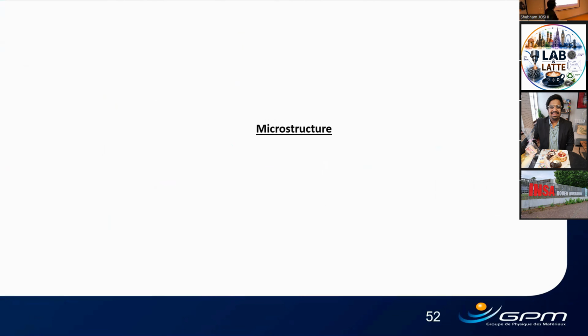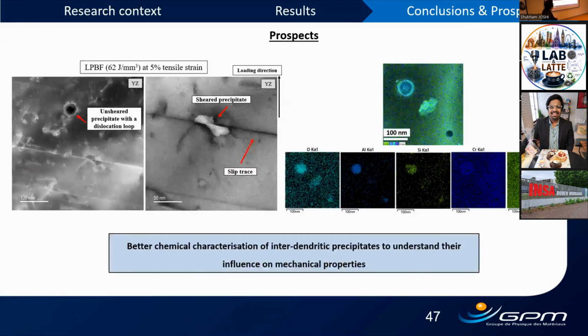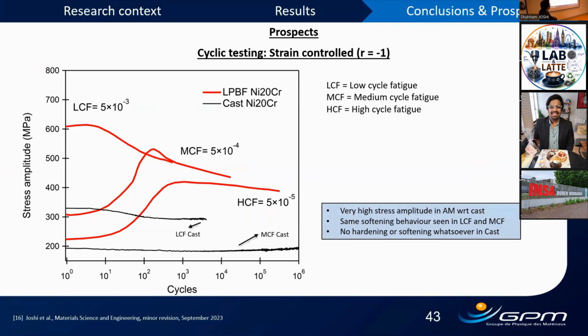Okay, anyway. What we did is, and it's also in the manuscript, we were really interested in what happens to the dislocations when it is still in the softening zone. So we stopped the MCF test at this point, at 1,000 cycles or 10,000 cycles. So it was an interrupted fatigue test.